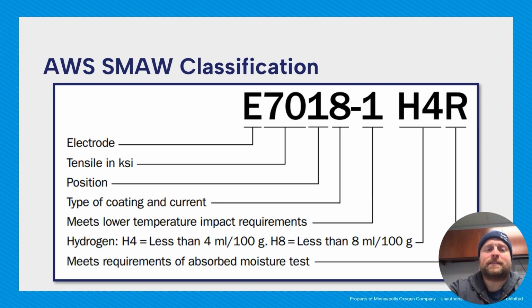The -1 means it meets lower temperature impact requirements. Basically, it's been tested for operating at a lower temperature. I believe it's tested at negative 20 degrees Fahrenheit with what's called a Charpy V-notch test, which measures how much it's going to move or break at that temperature. So when you have a 7018-1, it's been tested to be used in lower temperature service. The H4 is what our hydrogen levels are. Here, H4 is less than 4 milliliters per 100 grams of hydrogen. And the R means it meets requirements of the absorbed moisture test. They did a test for the amount of moisture it has when it leaves the factory. Why is this important?